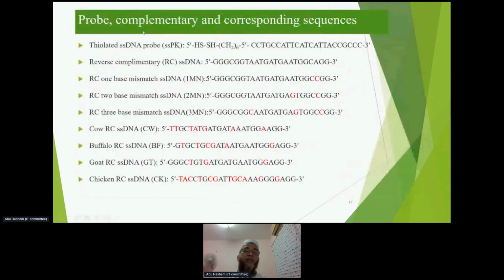Probes, complementary and corresponding DNA sequences are here. This is our probe DNA. We have modified it with a 6 carbon spacer arm to extrude it from the electrode surface, and a thiol modifier group to conjugate with gold nanoparticles through covalent bond formation. And secondary is the reverse complementary sequence. This will completely hybridize with the probe sequence. We also introduced several modifications, like 1, 2, and 3 base mismatches, which are indicated by red color. And we also intentionally included the complementary DNA of four other species: cow, buffalo, goat, and chicken.